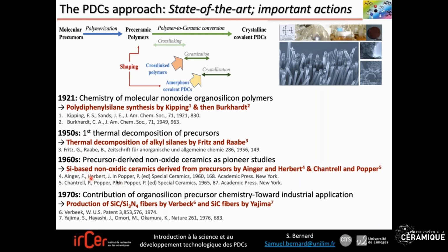Then these fundamental works led, a decade later, in the 70s, to a demonstration that PDCs can be prepared as fibers: silicon carbide and silicon nitride by Verbeek in Germany, and silicon carbide fibers by Yajima in Japan, in particular through the chemistry of organosilicon precursors, I mean from polycarbosilane, polysiloxane, and polysilazane. And in fact, today, the production of silicon carbide fibers is found in industry, and it is based on the process published by Yajima in '76, so more than 40 years ago. So these works marked the industrial potential of PDCs.